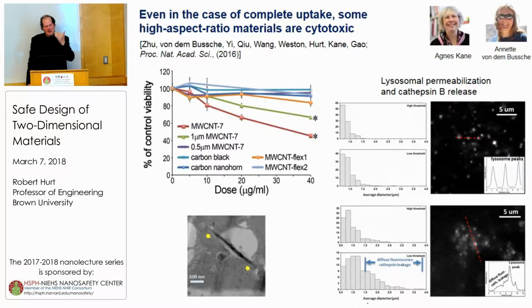So we did an oxidative cutting process using nitric acid and sonication. And you can cut the nanotubes and do a lot of image analysis and get mean sizes. Of course, you've changed their surface chemistry entirely. So what we did is re-annealed them to restore something like the original surface chemistry. So we have a nice sample set of nanotubes of different length with arguably the same surface chemistry. And you can show the progressive loss of this toxic effect when you go to 1 micron and then half a micron and down to nothing with the particulate forms.